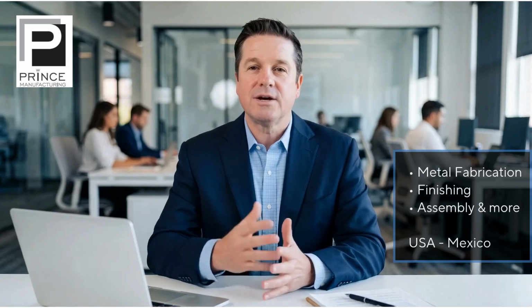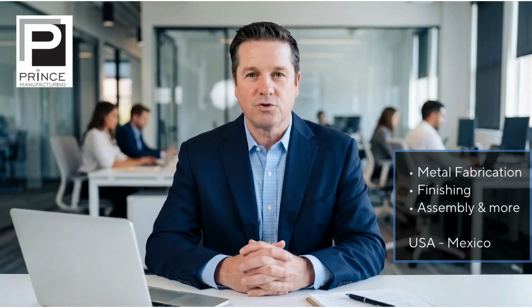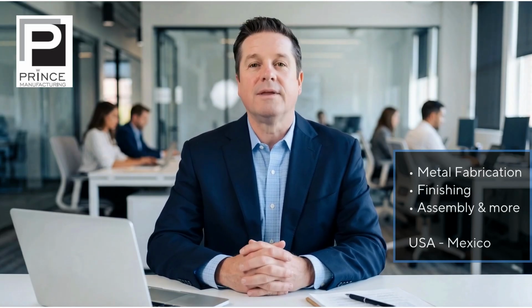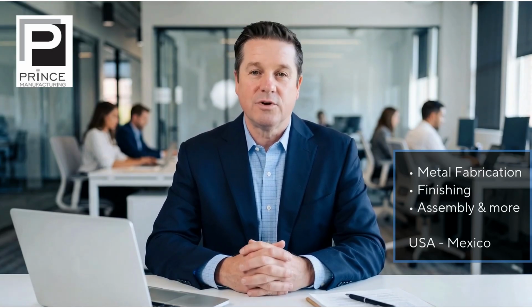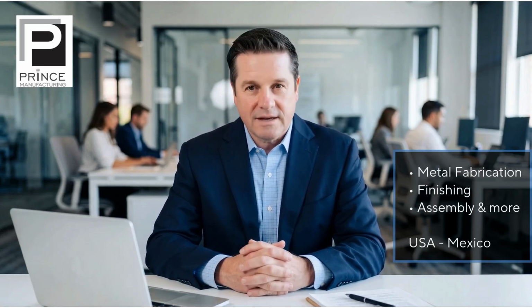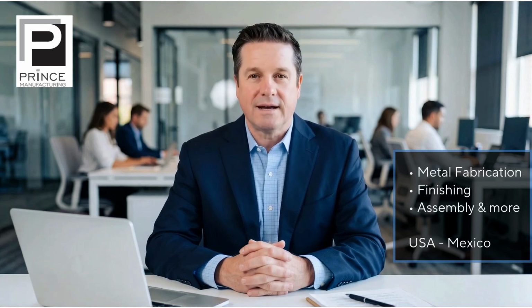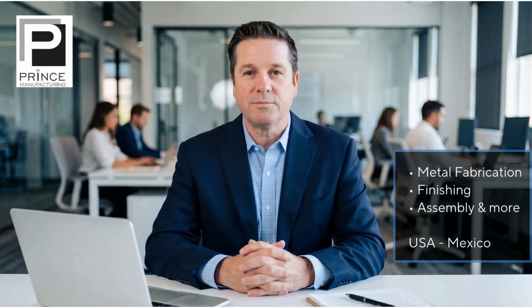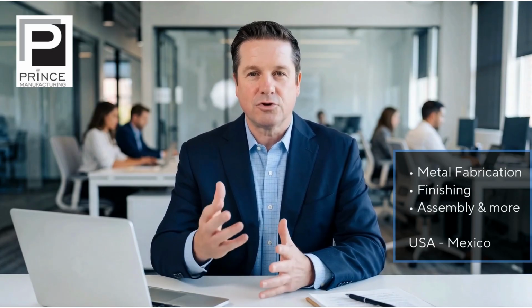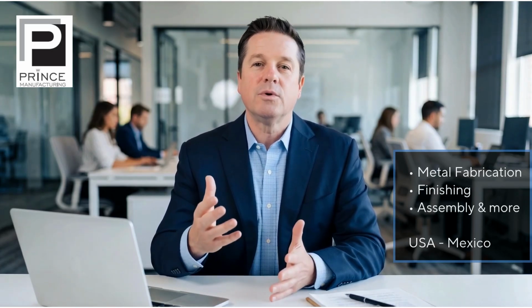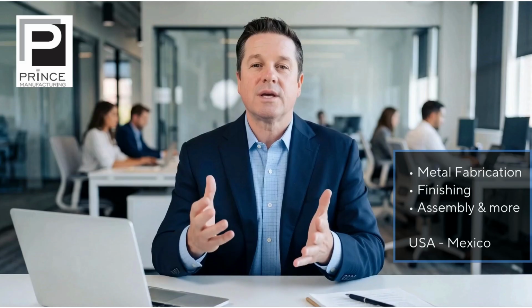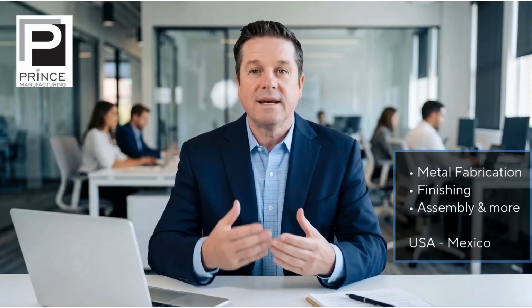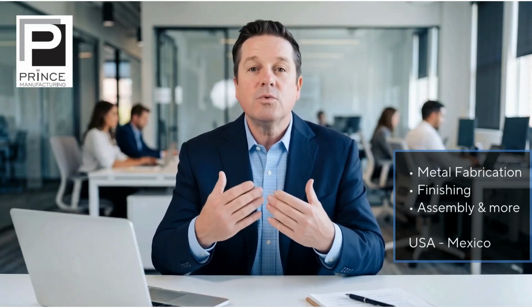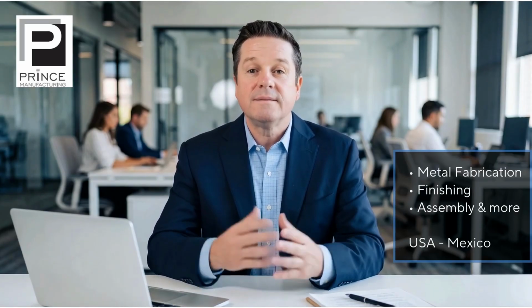Now let us look at E-coat. E-coat, also called electrophoretic coating or electrodeposition coating, applies paint through an electrically driven immersion process. The component is submerged in a coating bath. Electrical current causes coating material to deposit onto conductive surfaces. Because the component is immersed, E-coat can provide good coverage of complex geometries, including areas that may be difficult to reach with conventional spray application.